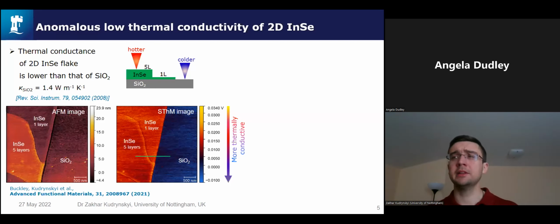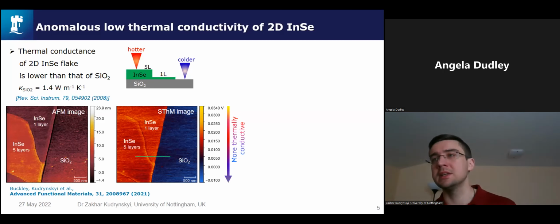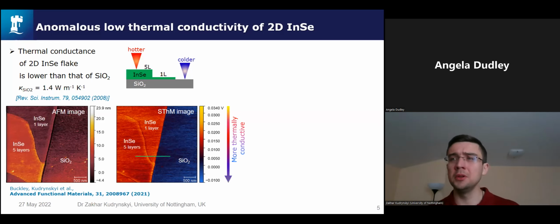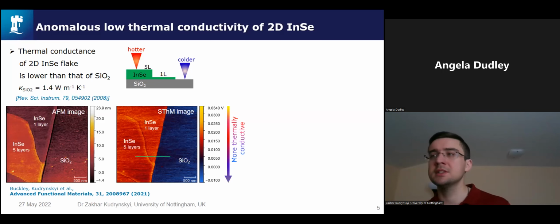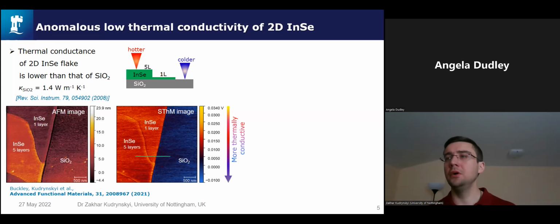This is quite an unexpected result, as in bulk state, indium selenide has a significantly higher thermal conductivity than silicon dioxide. And here we see the opposite effect in the 2D state. So this anomalous finding contrasts with previous theoretical studies in the literature, where the role of the substrate was not taken into account. The ability of 2D indium selenide to conduct heat depends on the thermal interfacial resistance between indium selenide and the supporting substrate.